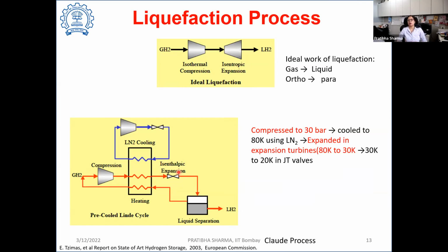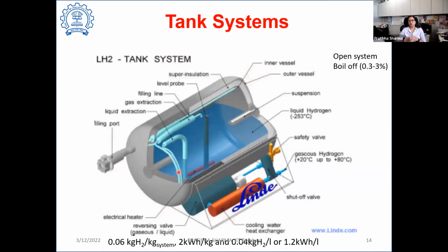So if we typically see a process of liquefaction, about 30 to 40% of the energy content goes into liquefaction. At the same time, when it is in the liquefied state being stored in a container, super insulated tanks have to be used because we are storing it at a temperature of 20 Kelvin and the delta T between the ambient and the liquid hydrogen is very high. When this temperature difference is very high, however good an insulated vessel you may use, there may be heat leakage from the ambient to the tank. And when there is heat leakage, a certain amount of hydrogen gets evaporated.